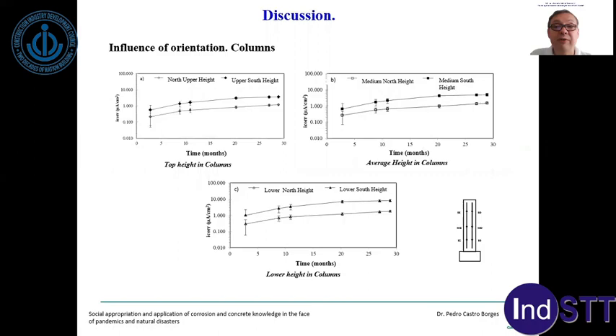And we are able to observe that very clearly on the columns of a house, with the help of the community. And the community knows what this means, and they are learning how to protect their palafitos. If now we see the influence of the orientation in beams, we can see a similar trend. The difference here is that the south zone is below. We have no very clear explanation for this, but we suspect that this is because most of them, or all of the beams, are protected, covered from the environment. So apparently, the influence of the environment is almost the same at any location. And that's the reason why we are observing very small cumulative corrosion rates, and it's not easy to find differences between the north, the central, and the south zone.